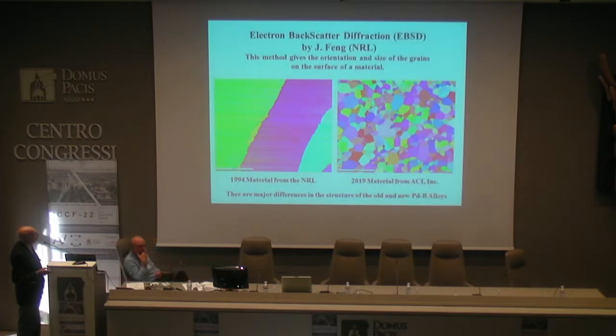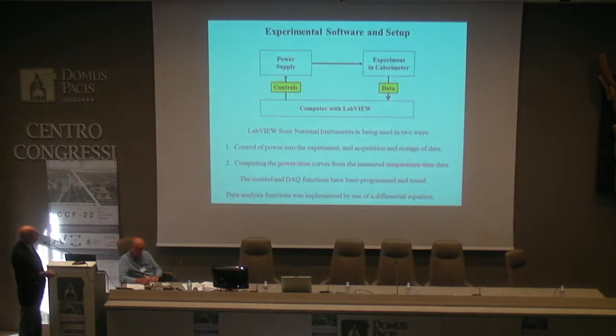We're also performing electron backscatter diffraction to get the orientation of the grains on the surface. And we were really surprised when we saw this because of the large difference in the grain size between the legacy material, the old material, and the new material. So we have major differences. Now, that we view as a problem. We would like to have the new material just like the old material, but we're not there yet. But we are able to characterize the structure, and I won't show it, but also the composition of the materials in both cases.